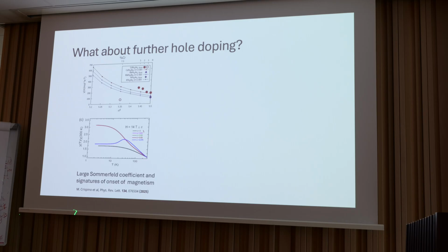So I think someone else will be talking about this paper specifically later, so I won't say too much about it. But you can ask, what about further hole doping? And so they chromium dope cesium-122 to try and push past that 5.5 filling towards true half filling. And what they see is these very large Sommerfeld coefficients, which I think are the largest of any iron family. And then they start to see the signatures of the onset of magnetism.